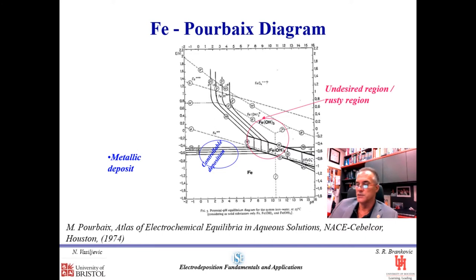So generally, using the example of iron, I would like to tell you that just looking simply at the Pourbaix diagram, you do not want to create a solution for iron, unless you're using some complexing agents and other stuff, which are too high in pH, because it would be precipitating iron hydroxide, whether it's iron 2 or iron 3 hydroxide, it will start to precipitate.